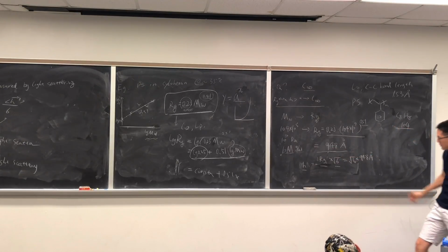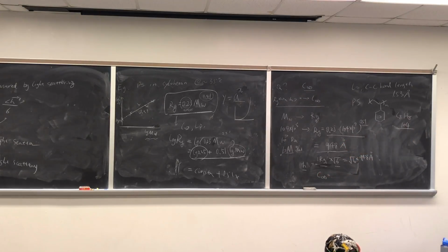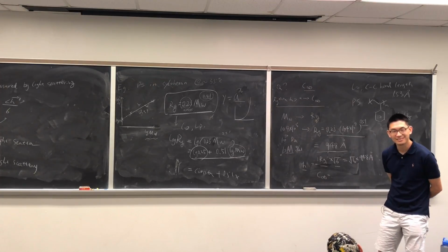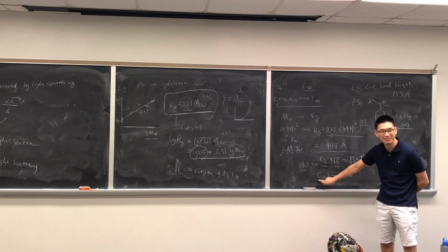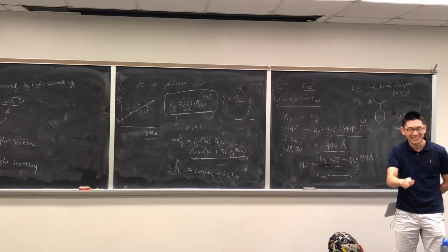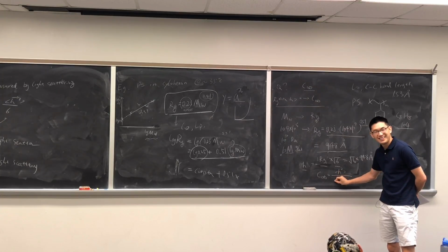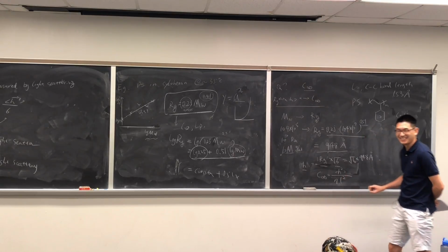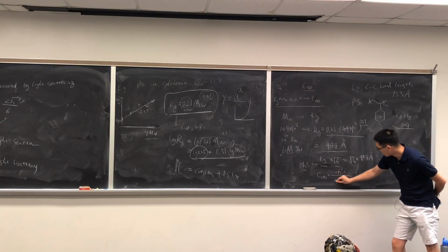Okay, so how about this characteristic ratio? This is a parameter that you can use to understand if the chain is rigid or not. So then C infinity will equal to h squared over n times l squared. N L squared, right? Cool, good job. So what we're going to do now is, do we know all the parameters here?